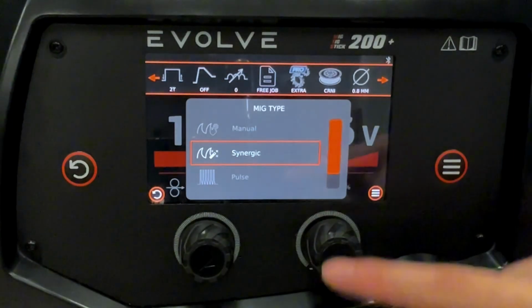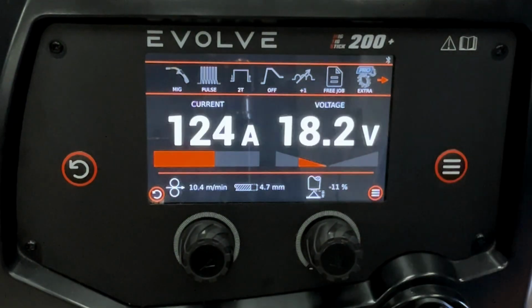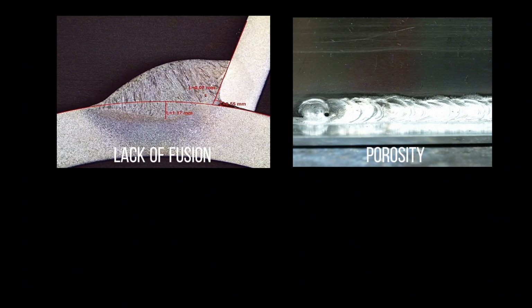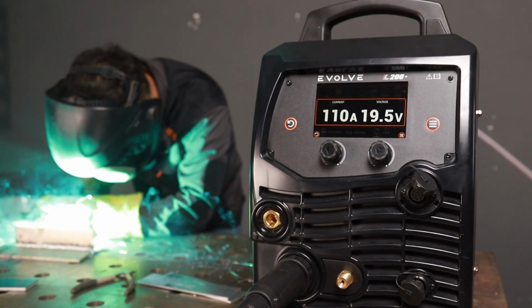Pulse welding processes like pulse MIG and pulse TIG help minimize aluminum welding issues such as lack of fusion, porosity, burn-through, and warping. They offer better control of heat input and provide directional control over the weld puddle, ensuring a good bead appearance. Within a single pulse, there is a peak current accompanied by a background current. The peak current provides sufficient heat for fusion, while the background current maintains the arc and allows the weld puddle to freeze slightly, preventing burn-through.